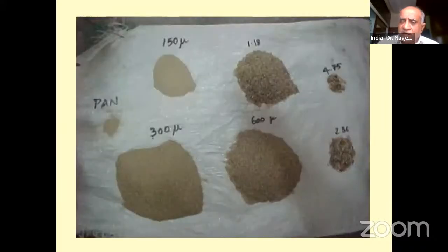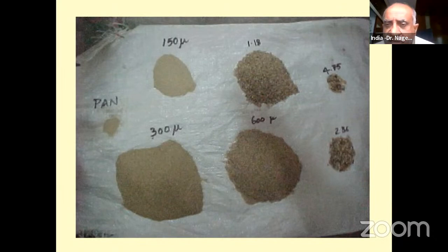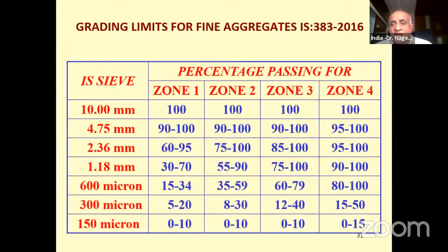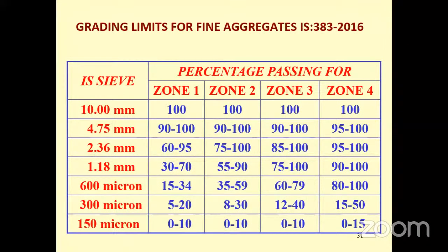So when you carry out the sieve analysis, this is what you are going to get. The 300 micron sieve fraction, 150 micron, 1.18 mm, 600 micron, 4.75 mm and 2.36 mm. Of all these, if you observe, 600 micron decides the grade zone of sand. If you look at 600 micron, the percentage passing is 15 to 34 for zone 1, 35 to 59 for zone 2, 60 to 79 for zone 3, and 80 to 100 for zone 4.